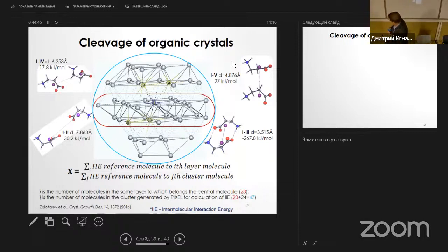For example, this X attribute, one number, allowed us to find these structures among approximately half a million other structures. This is actually a very exciting example, because when Italians asked us to find such structures, we processed about half a million structures and found just 11 with the required property. Then our people went to Italy and synthesized these 11 compounds, and all of them fitted this property. So the prediction here was 100%. It's a very rare case, of course, but it's a fact.